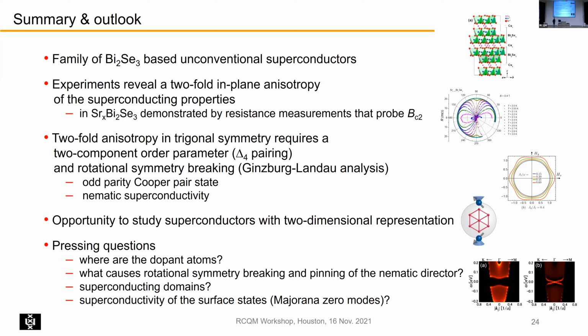Yeah, that's true. So second, and maybe this is more of a theoretical question, but it certainly relates to the data. The conclusions about necessity of a two-component order parameter assume that the normal state is completely isotropic, right? Yes. So maybe you have some structure of the dopant atoms, and this gives anisotropy in the normal state, which can be inherited by the superconducting state with just a single-component order parameter. Isn't that true? If I have an anisotropic normal state, then a lot of these conclusions about things being more exotic don't follow. Yes, but then you don't have the trigonal symmetry anymore. You mean it would become orthorhombic, or you would have some distortion? Right. But I understood that the normal states are sometimes isotropic.